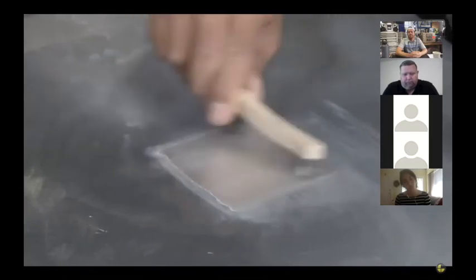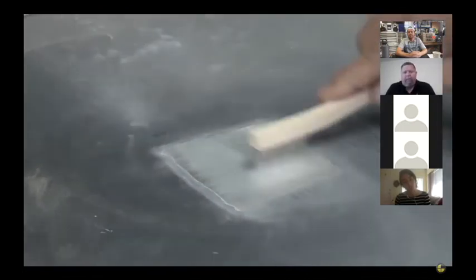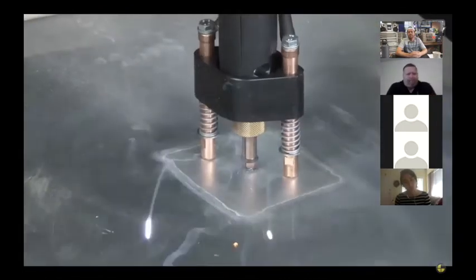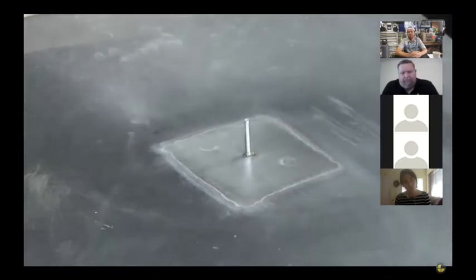It is critical to get all that oxidation off. Aluminum oxidizes immediately when it's exposed, so it is very important to put your stud on immediately after you brush it and get all the oxidation off. Proper panel prep will ensure good adhesion of the stud.